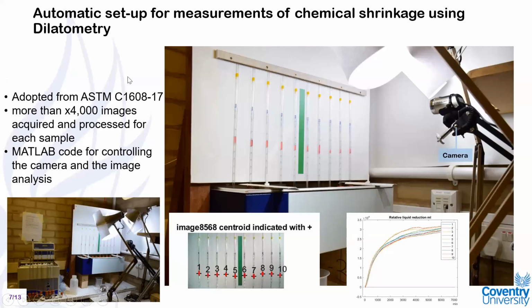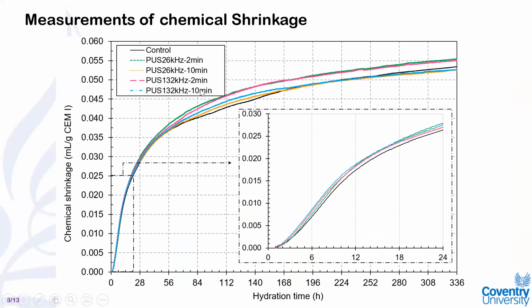We developed automated dilatometry for measuring chemical shrinkage in cement paste. We needed a precise setup and method because the difference between the various ultrasonic frequencies was not really significant. Here you can see the result for measurement of chemical shrinkage. As you can see, the shorter sonication, both at 26 kilohertz, which was the higher sonication energy, and 132, leads to an acceleration of the rate of chemical shrinkage, and it might be related to the extent of hydration.